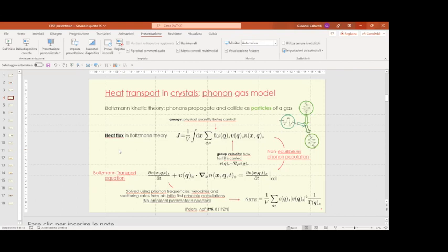So it's like considering the first order anharmonicity, so the third order interatomic force constant matrix, as a perturbative Hamiltonian, and you can do perturbation theory. Using Fermi golden rule, you can compute the scattering rates from that anharmonic interaction Hamiltonian, and it's the easiest formula you can make, basically. Okay, and so you take into account this effect, so yes.